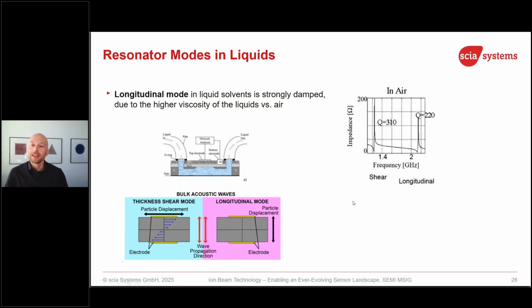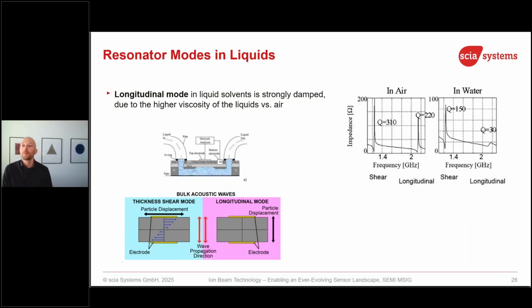Now we have to put our sensor in a liquid. What happens? If we look at the resonance frequencies of those two modes, and at the Q factor, which means how sharp our resonance is, we see that in air we have a nice peak for the longitudinal and the shear mode, both. Now we put our sensor in water. What happens? That mode here, oscillating perpendicular to the surface, gets a high damping. It's moving against the water, so we don't have a nice peak anymore. So that's not a very nice frequency where we would do measurements here.